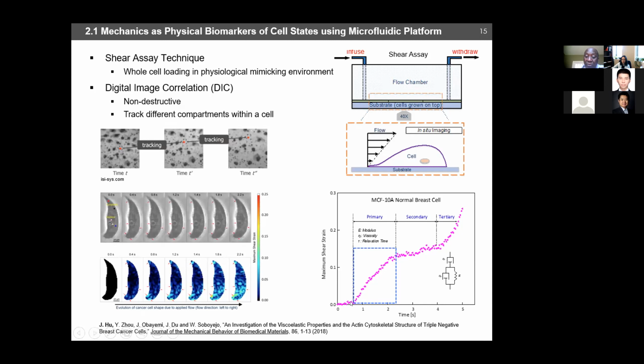You see then that you go from a primary creep to a secondary creep regime, and then to a tertiary creep regime. And so from experiments, we were able to show that the cells undergo this kind of classical creep behavior. And you can get this information both in the nucleus and in the cytoplasm. And so in that way, you can now begin to fit the creep data to spring dashpot models that characterize the creep deformation of normal cells, as well as cancerous cells.